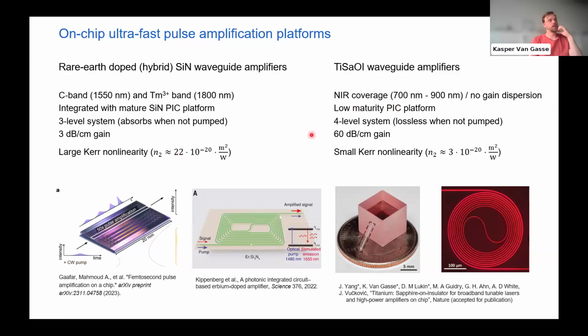If you look at titanium sapphire, on the other hand, it's an ultra broadband gain profile. So it means that you have no gain dispersion. It's a 4-level system, so it doesn't really absorb even when it's not pumped. That really makes the pump management a lot easier. The gain is very high, so you can make your amplifier very, very short. And that means you will have to take less dispersion and other effects into account. And on top of that, the Kerr nonlinearity of the titanium sapphire amplifier is very tiny. It's only 1/10 of that of nitride. So you can get away with a lot more in terms of pulse amplification.